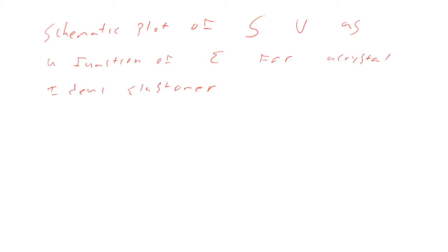Right? So what does internal energy versus strain for an elastomer look like? It's not changing. It's constant, right? What about entropy? Decreasing. Is the curvature concave up or concave down? Entropy decreases when it stretches.